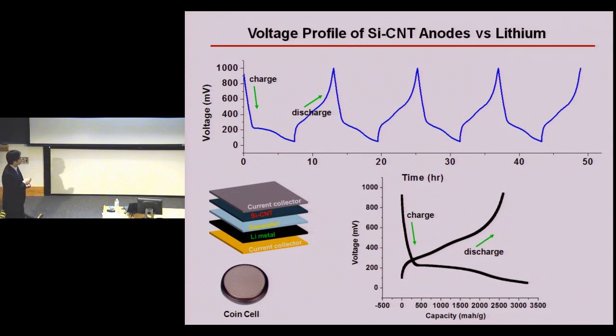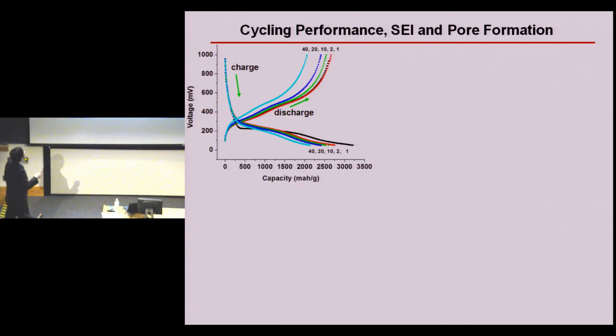So in the battery field, people normally use this kind of voltage profile. The voltage is still the same here, but the x-axis is normalized by the time of charging, the current. So this is the time, this is the current, normalized by the weight, which is called the capacity. This kind of voltage profile is very commonly seen in the battery literature. So we can do this kind of voltage profile for different cycles. This is the charge profile, and this is the discharge profile for different cycle numbers. From this kind of voltage profile, we can get very important information out.